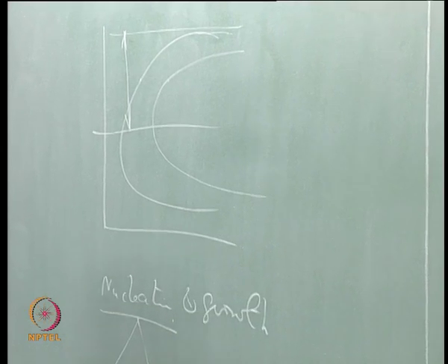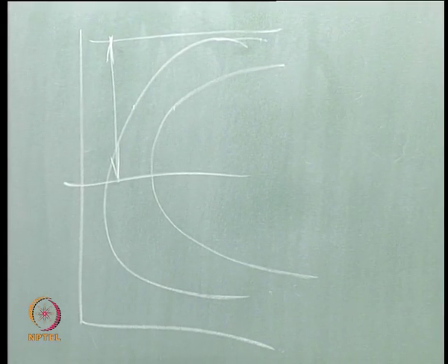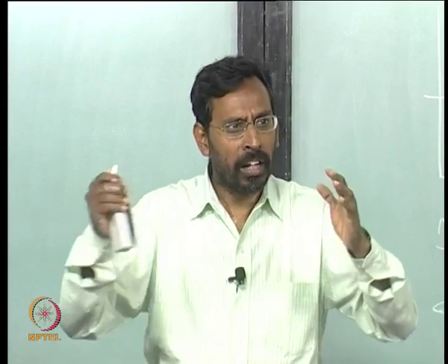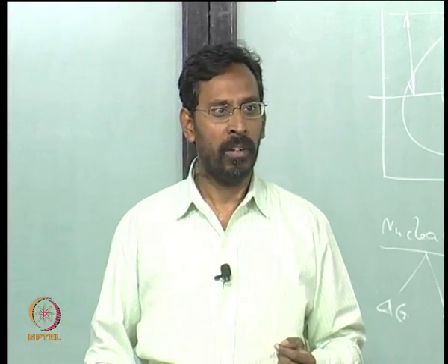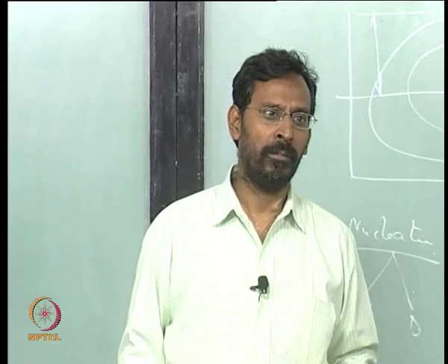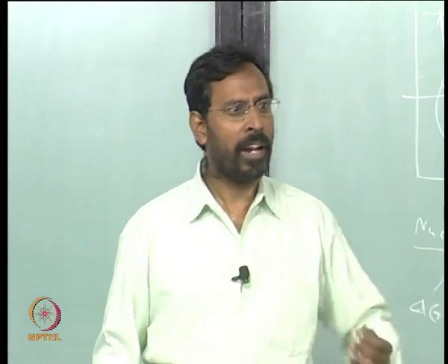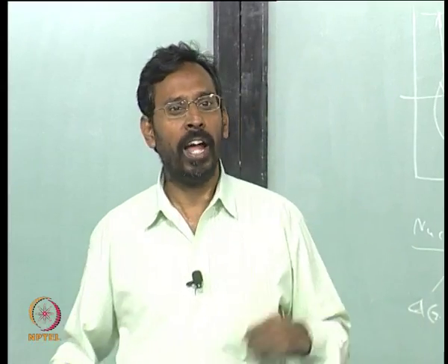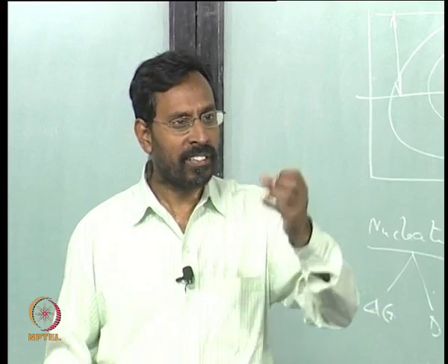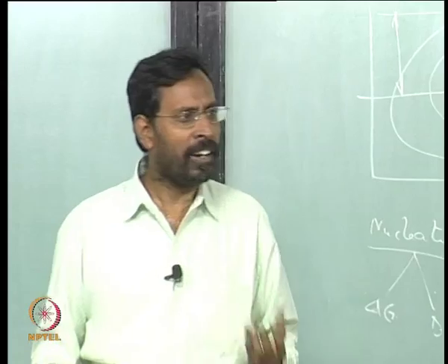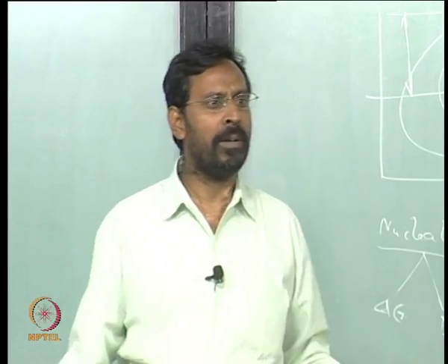That is where you will always see diffusion dominates, and that is the reason you actually see even glasses forming. The fact that a glass forms from a liquid is an indication that nucleation is not able to happen. The atoms are not able to come together to form that nucleus, and the nucleus is not able to grow. If that could happen, why would glass come out? In fact, long back Turnbull made a profound statement that every liquid would like to become a glass unless crystallization intervenes.